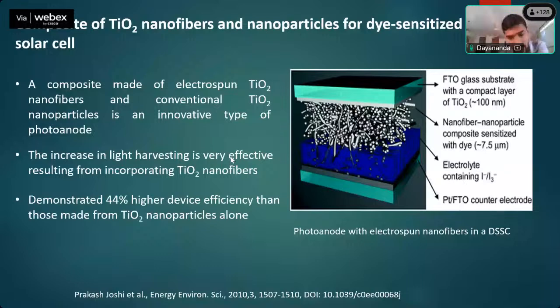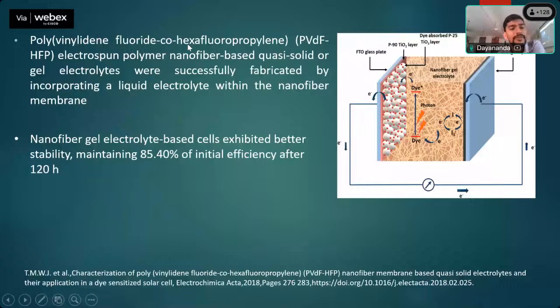So over to another technique to modify the electrolyte. They made a nanofiber mat using PVDF-HFP, a fluoropropylene, and prepared the nanofiber as an electrolyte. The nanofiber mat was made, then a few drops were adsorbed on the surface of the mat, and then it was made to contact with the photoanode. This nanofiber gel electrolyte-based cell exhibited better stability, maintaining 85.40% efficiency after 120 hours.